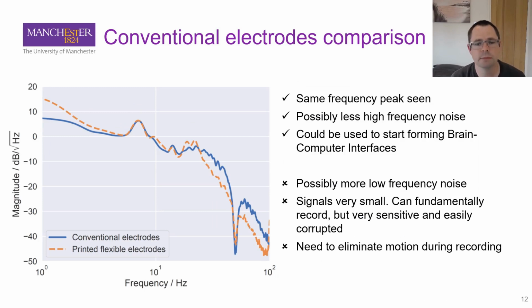We also repeated the test, but with just conventional pre-gelled electrodes stuck on behind the ear, and there we can see that the height of the peak we measure in the frequency domain is exactly the same using the 2 different types of electrodes. So that's a very promising result. With our electrodes we see possibly less high frequency noise, but possibly slightly more low frequency noise. What we also find is that all of these are very sensitive to external interferers. So things like motion, things like moving the head, and so on.